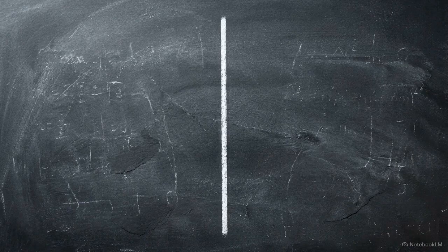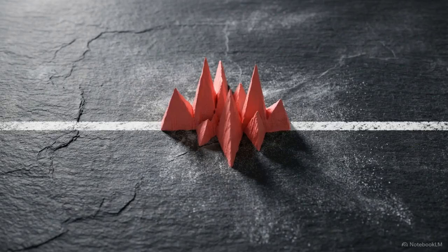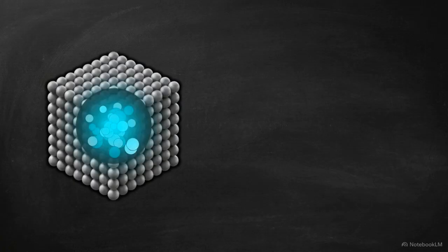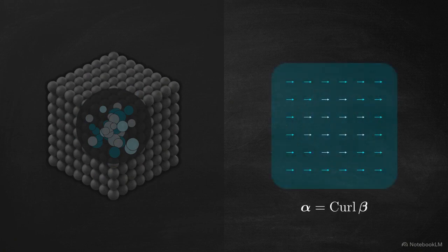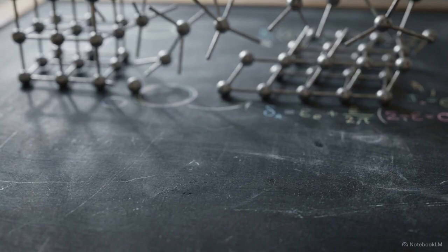This allows physicists to replace an isolated Volterra line, which produces infinite stresses at an infinitely sharp point, with a smoothed, regularized continuous core. By treating the defect this way, the Nye tensor formulation successfully decouples the conserved translational charge from the highly non-uniform singular strain at the exact center of the atomic core. But the Nye tensor relies on a small strain approximation.